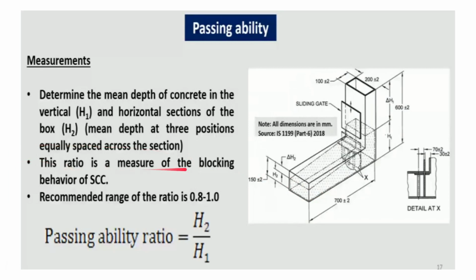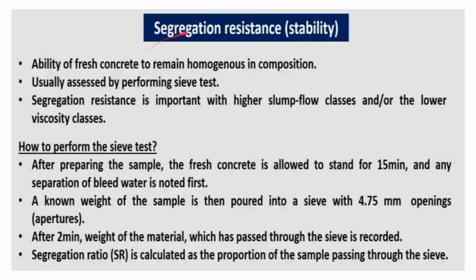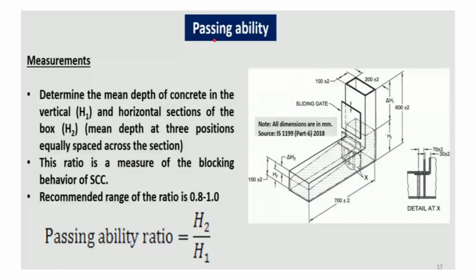This ratio is a measure of the blocking behavior of SCC. It measures how the SCC passes through the reinforcement. The recommended range of the ratio is 0.8 to 1.0. So the passing ability ratio, which is h2 by h1, should have a value between 0.8 and 1.0 for it to be called self compacting concrete. So that is basically the passing ability.